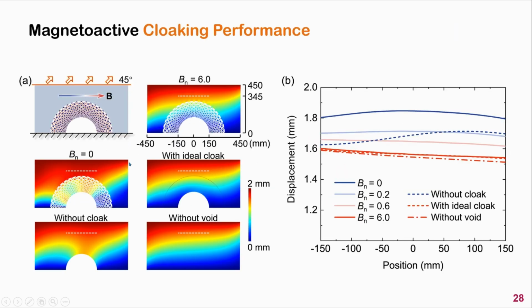Okay, then the performance of the lattice cloak is examined using finite element simulation in COMSOL. Note that to save computational cost, here we consider the half cloak model. And in the simulation, the bottom of the system is fixed and an external and uniform displacement load is applied to its top boundary. We record the response of the system under different intensity of magnetic field, and for each case, the total displacement profile at the white dashed line is measured, as presented here.